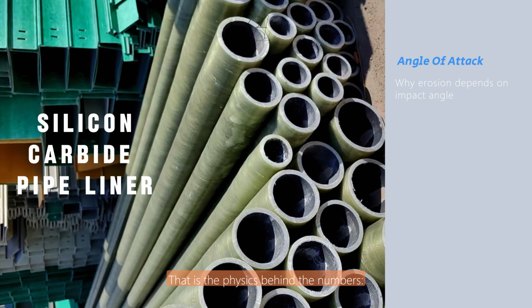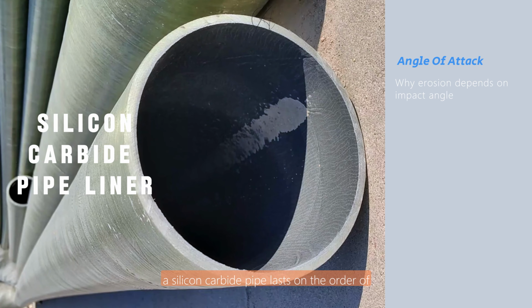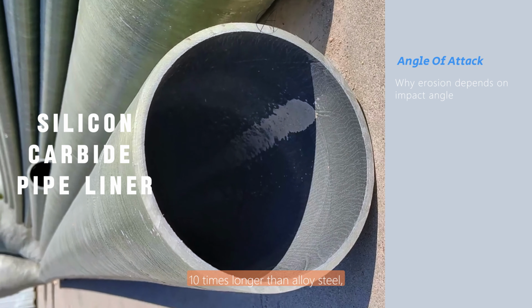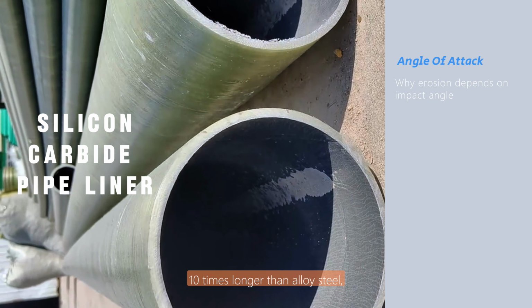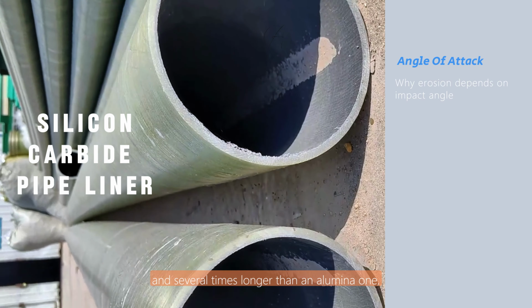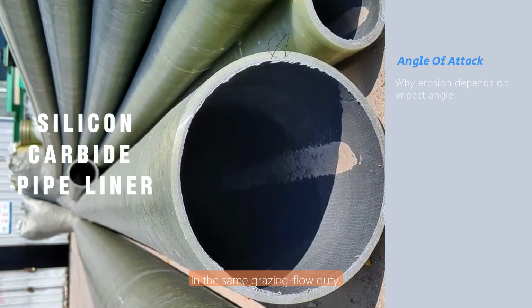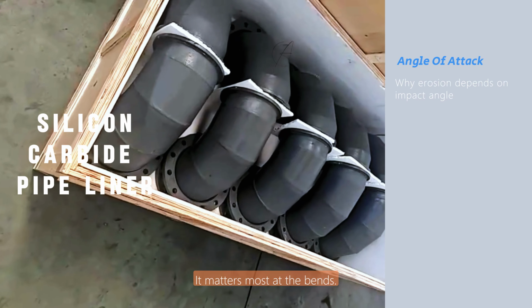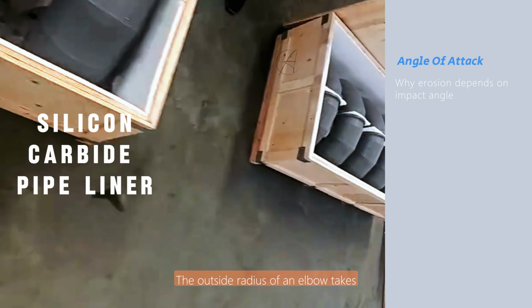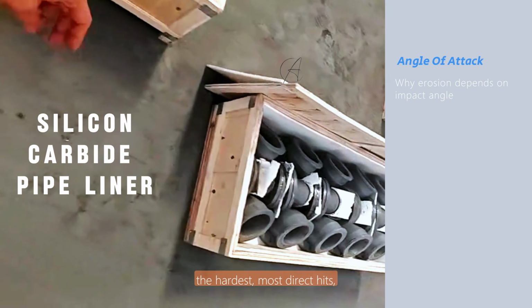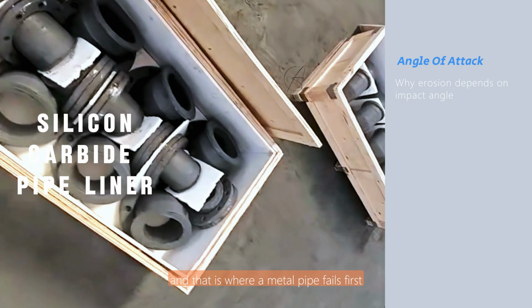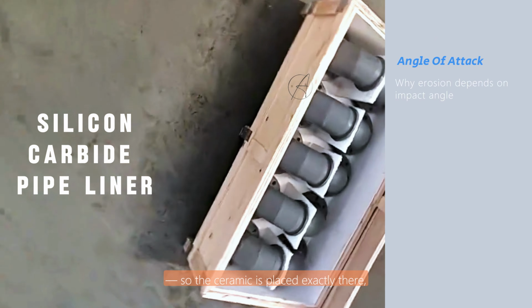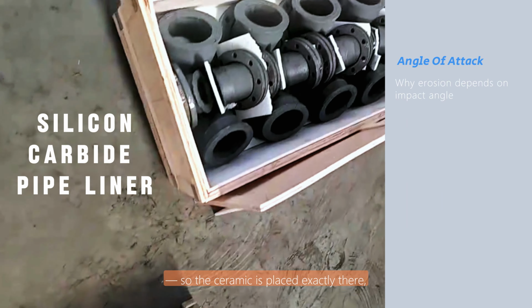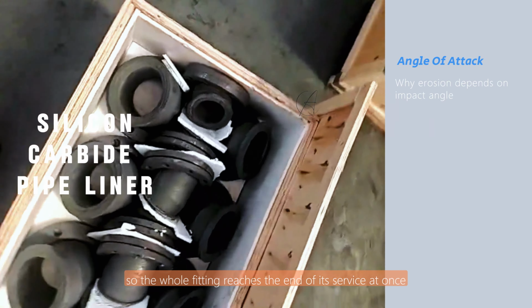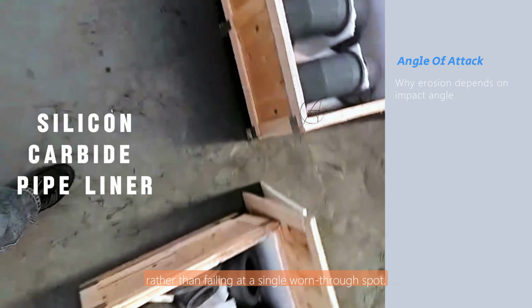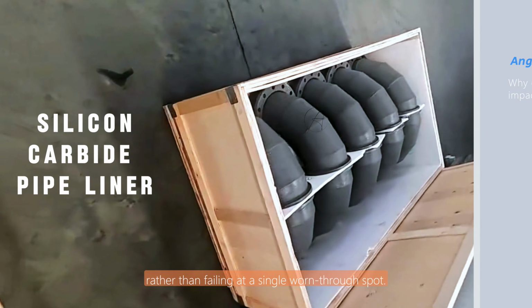That is the physics behind the numbers. A silicon carbide pipe lasts on the order of 10 times longer than alloy steel, and several times longer than an alumina one, in the same grazing flow duty. It matters most at the bends. The outside radius of an elbow takes the hardest, most direct hits, and that is where a metal pipe fails first. So the ceramic is placed exactly there, evening out the wear life so the whole fitting reaches the end of its service at once rather than failing at a single worn-through spot.